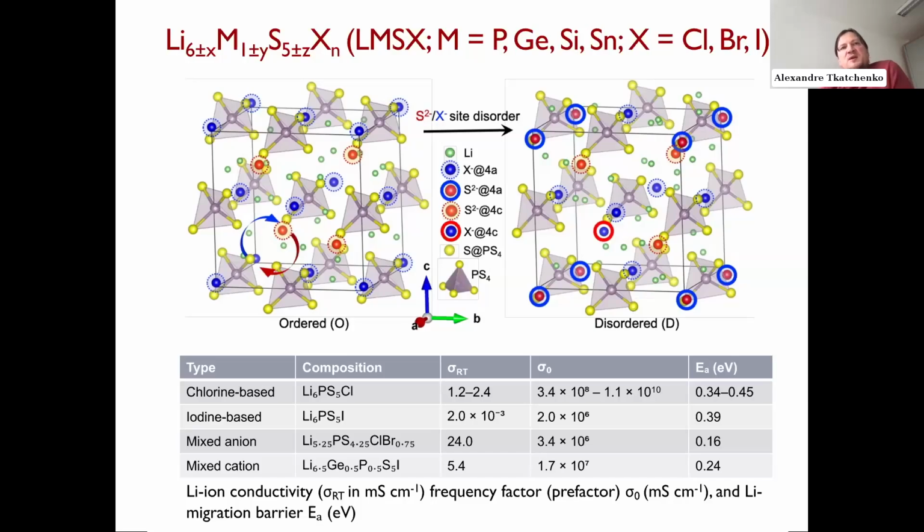I think you probably need just a few thousand calculations for a few thousand structures, which would allow you to construct general machine learning force fields for this class of materials. We haven't done it, so it might be more complex than that. But I wouldn't recommend running explicit ab initio MD on these systems because I think that with machine learning force fields, that's the way to go now.